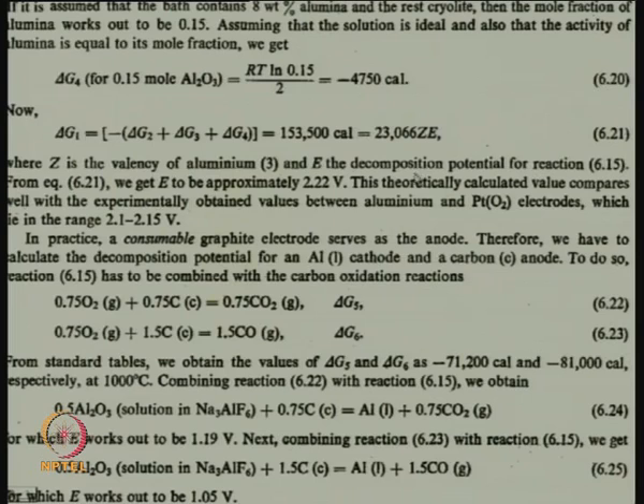This E will give us the decomposition potential, and by doing this calculation, the theoretical decomposition potential for a solution containing 8% alumina comes out to be 2.22 volts. This theoretically calculated value compares with experimentally obtained values between aluminum and platinum oxygen electrodes, which lie in the range 2.1 to 2.15. So, theoretically we have calculated a value which is very similar to what can actually be obtained experimentally in a lab using platinum electrode and aluminum electrode.